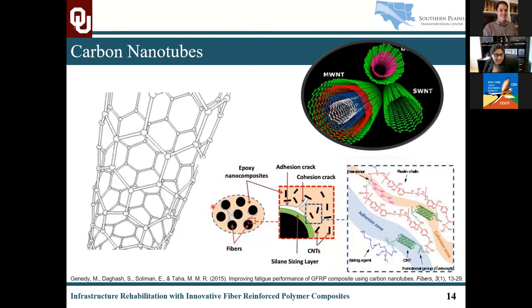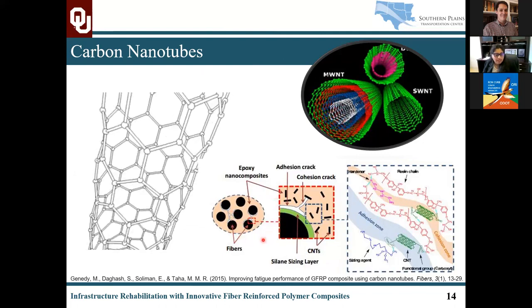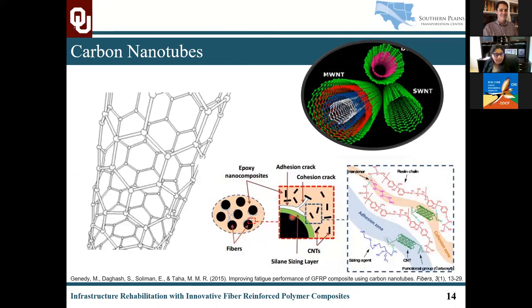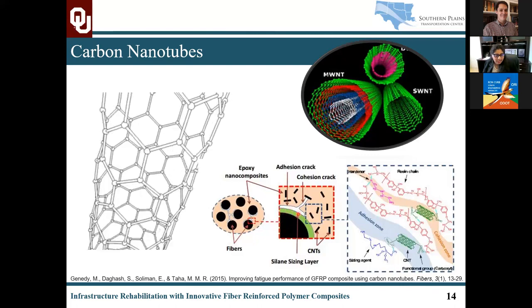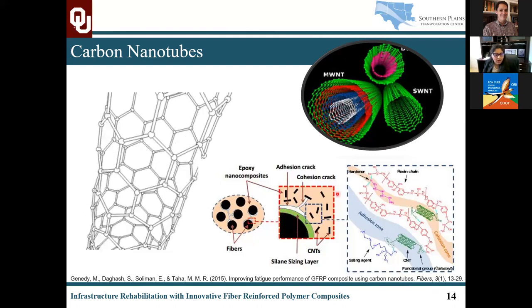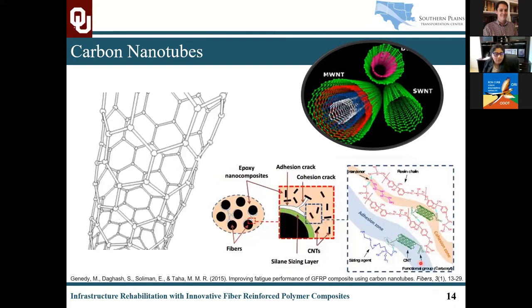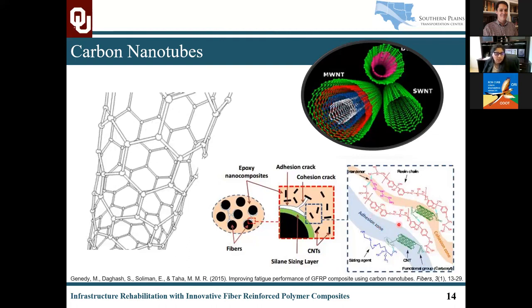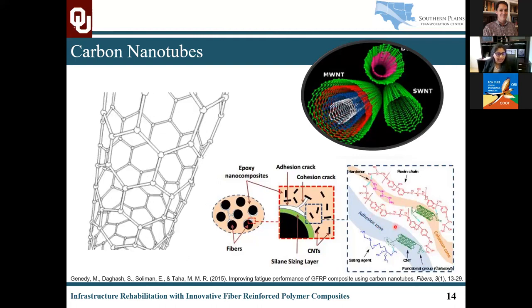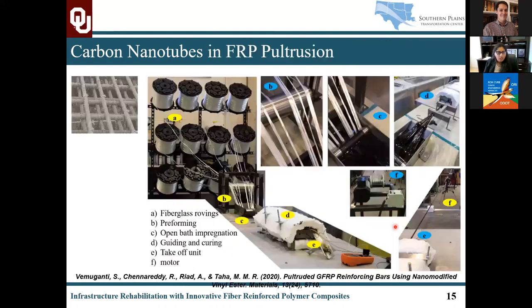If we look at these epoxy nanocomposites, the fiber that has silane sizing agent reacts with the carbon nanotubes in the resin, forming a much better, improved chemical reaction and resulting bond. Looking at the applications of this, one particular project that I was involved with is how we can improve the shear strength of FRP particularly.